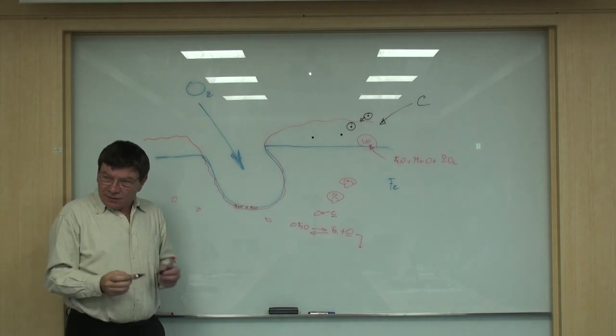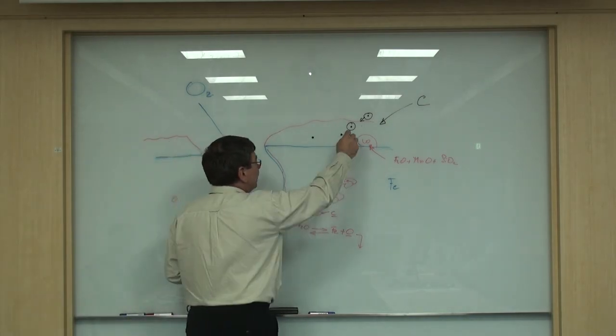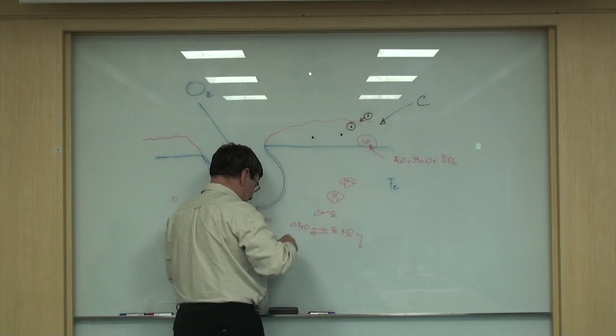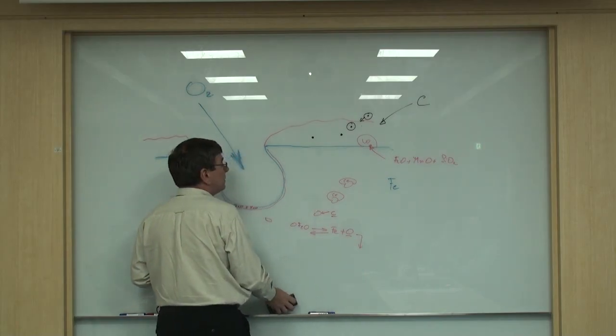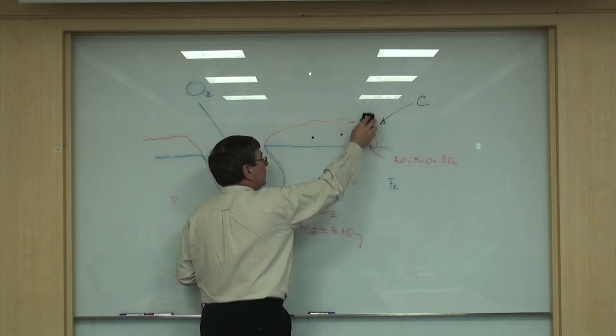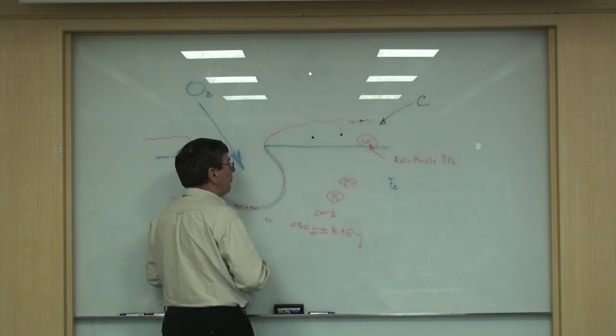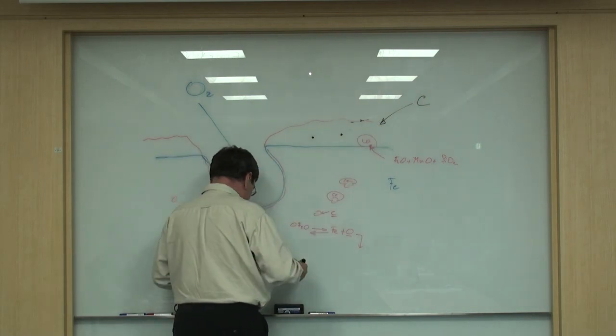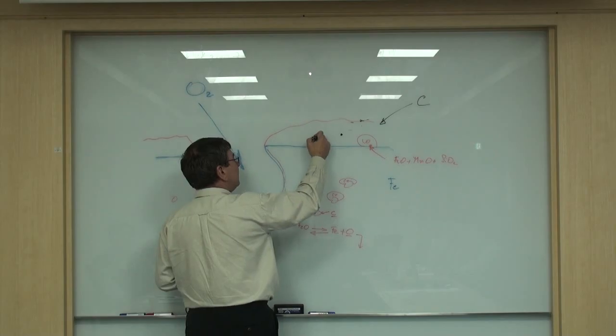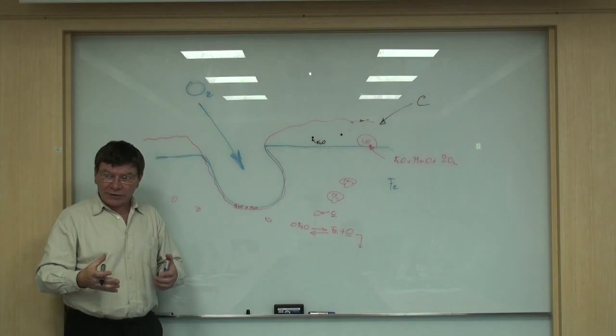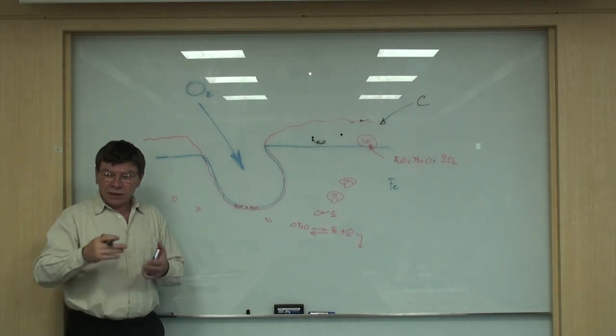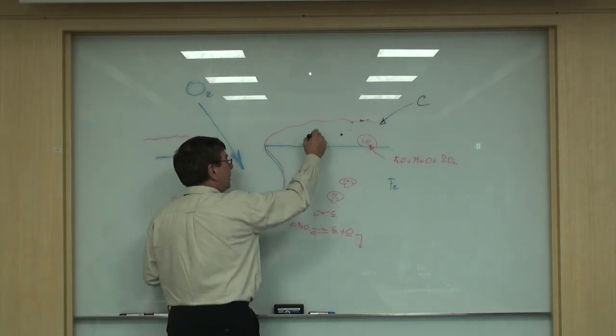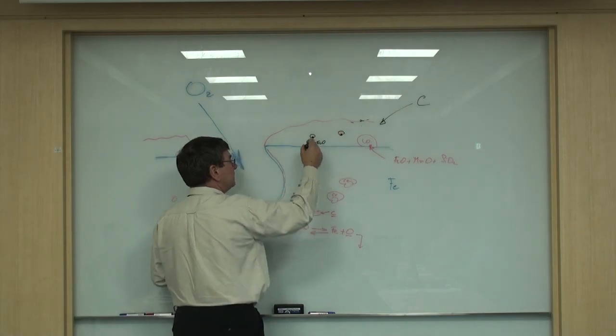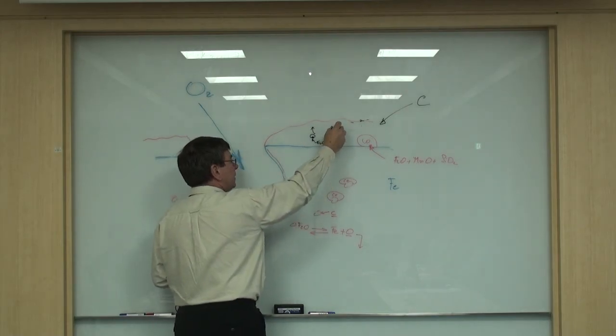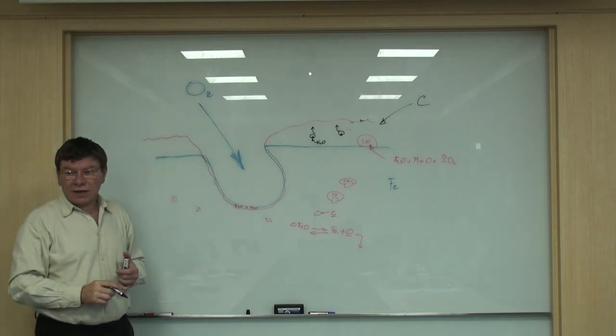How can it react? Not possible. But if you are able to avoid these volatiles, then you have a carbon particle moving into the slag and meeting the FeO, because the FeO is dissolved in the slag, so it's liquid, it's easy to react, and you create small bubbles, which are migrating to the surface of the slag.